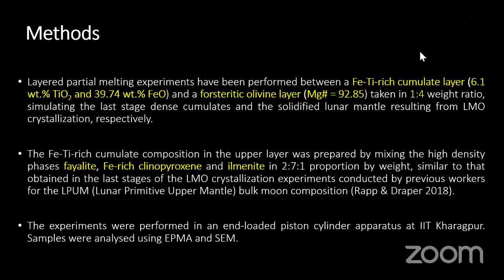Now, coming to our methods, we have conducted a few partial melting experiments. These are the first high pressure, high temperature experiments performed in the field of geology from India, using a piston cylinder apparatus at IIT Kharagpur. The assembly that we have chosen is a 1/2-inch talc and pyrex assembly. The experimental design includes a bottom layer of forsteritic olivine that takes about 80% of the mass, and that is very Mg-rich, with an Mg number of about 92.85.